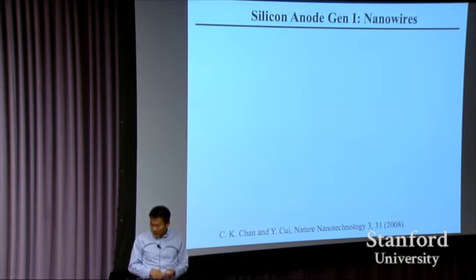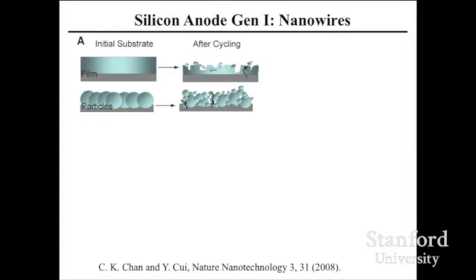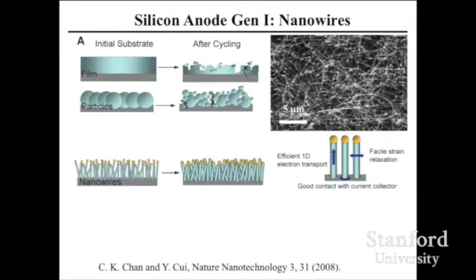Now, the first paper I published with a graduate student to really go into battery research is this silicon nanowire. As soon as I learned about the silicon anode problem, this became a natural thought. Why don't we use a nanowire shape? We know the film and the big particles all break. But the nanowires are small enough that they expand, contract, expand and contract, but their diameter is small enough, and with free volume around the nanowire, they don't break. As a first-order idea, we went in and tried it. It works. So you can start to cycle your batteries.